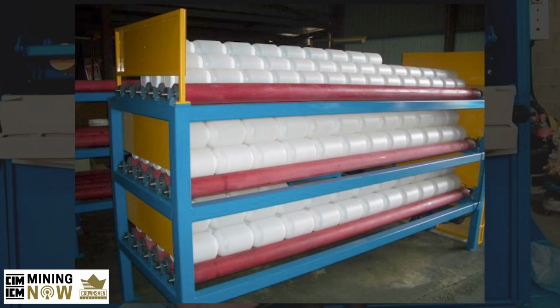When you do something like a fire assay or, say, a photon assay, which is the new technology, they're very good at determining what gold might be in the ore before it enters into the circuit. What it doesn't tell you is how much of that is recoverable through your cyanidation process. So what a bottle roll is simply, it's all in the name. It's a bottle or a jar where you'll put a known amount of, say, a kilogram of the ore, pulverized quite fine to mimic what's happening in the plant. You'll add an amount of water plus cyanide and maybe some lime chemicals for pH control.